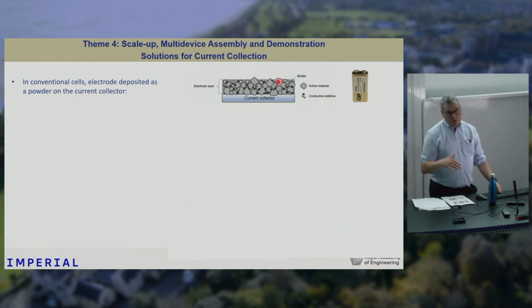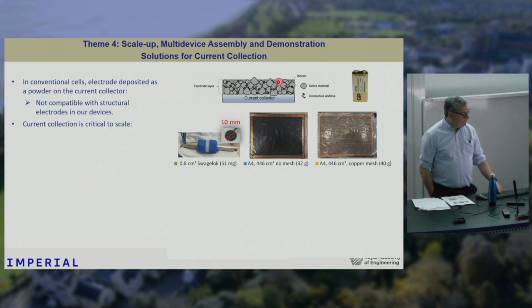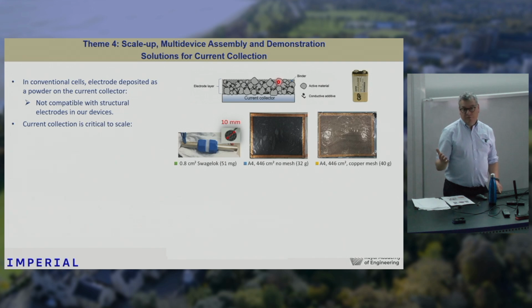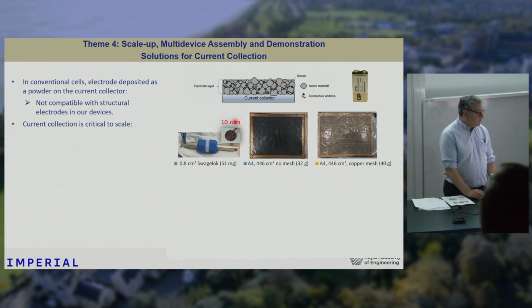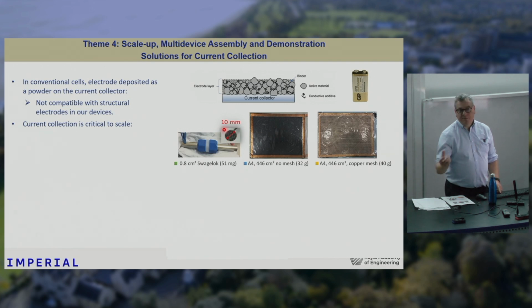The advantage we have with our material is the fibers, the electrodes, are carrying the mechanical load. So the current collectors could be very, very thin. So this is something we're exploring. And really where this started to hit home to us was when we started to look at scale up of our devices. So we took a Swagelok cell, which is this 10mm diameter device, took exactly the same material, and we made an A4 sheet of material, and then looked at two different types of current collectors, either this current collector around the edge or having this grid, for instance, as the current collector.